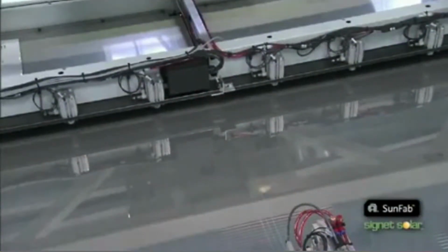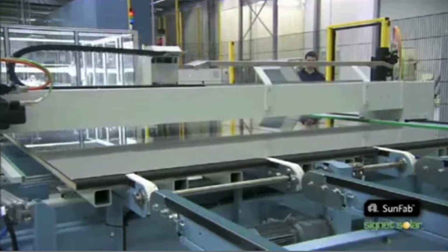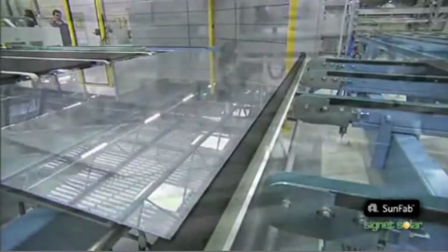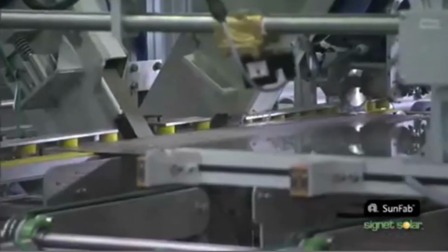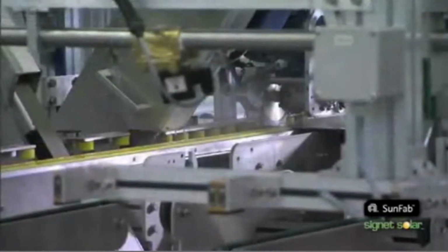Then the so-called shunt removal system further isolates the sides of the substrate to prevent shunt leakages. Since 5.7 square meter modules are not always so convenient, the modules can be cut into half or quarter size depending on the customer's requirements. Next, the photoactive film on the edges of the module is removed for greater reliability. The film on the edge might limit the current output of the module due to imperfections in the production process and is therefore removed.